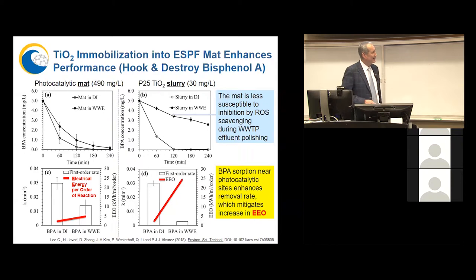So this red line is something called the electrical energy per order of reaction. It's essentially how much electricity do you need to operate these UV lamps so that you can remove the pollutant by one order of magnitude. And you can see that for this slurry, the electricity requirements increased by 11-fold versus only 2-fold for the photocatalytic mat. Again, because you have a material that is more selective about removing the target pollutant, so you need less energy to take care of it.